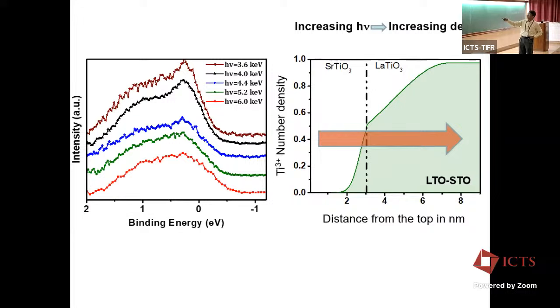You have this peak structure, very close to the Fermi energy, and then this broad thing, which is believed to be the signature of the lower Hubbard band. And you see that this change from the same sample is happening because you're changing the photon energy. When you are at the lower photon energy, so you're looking at the top level, you have a more coherent feature.